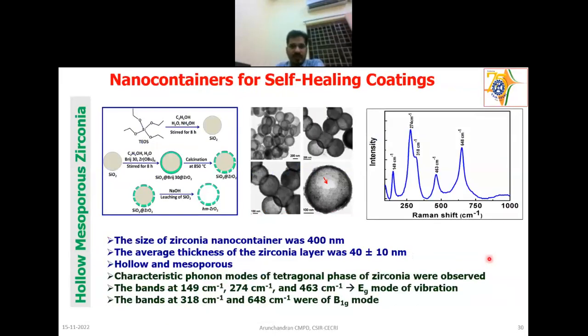This is another capsule which we made in our laboratory. This is actually a hollow mesoporous zirconia capsule we made. Starting with the Stöber method, we made some solid silica particles. And on the solid silica particle, we coated this zirconium moiety here. Some surfactant was also used. And during calcination, the surfactant is removed. So you have the pores here.